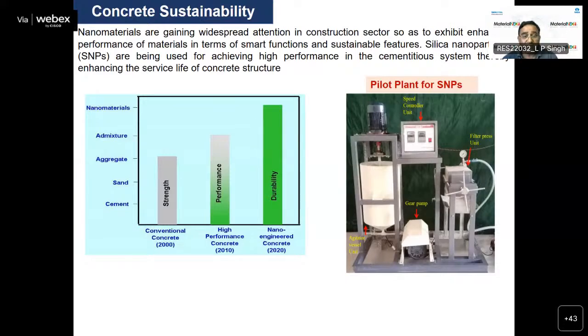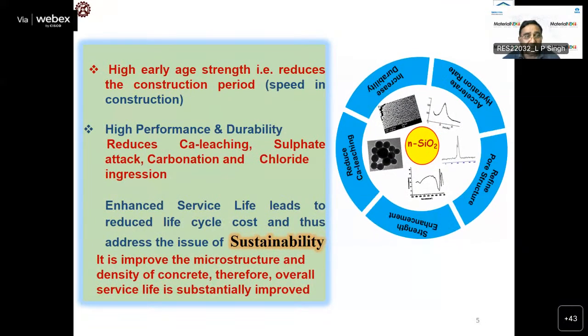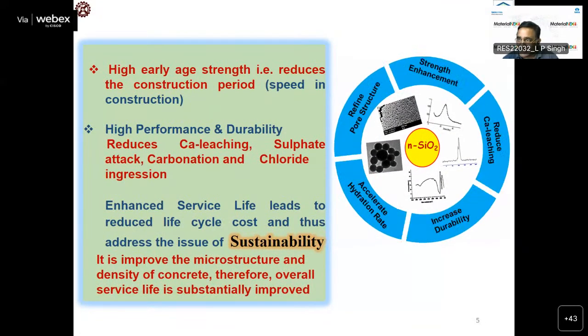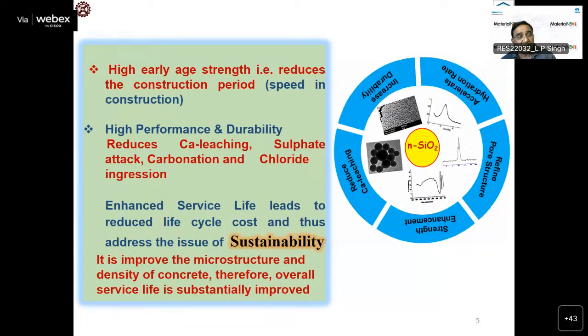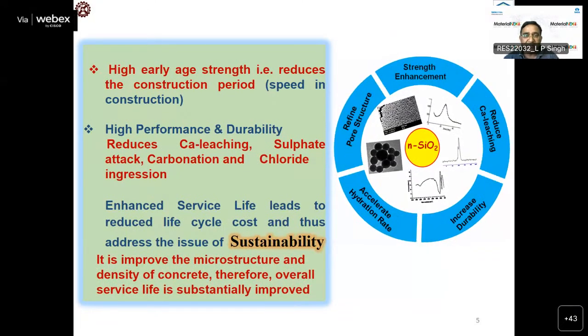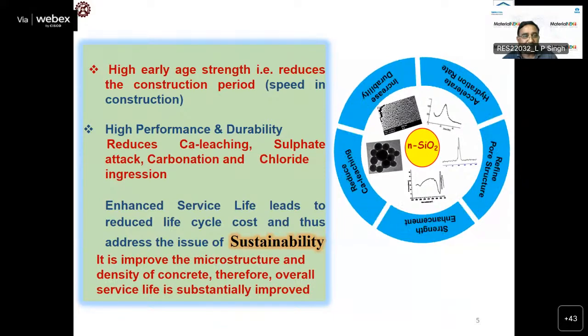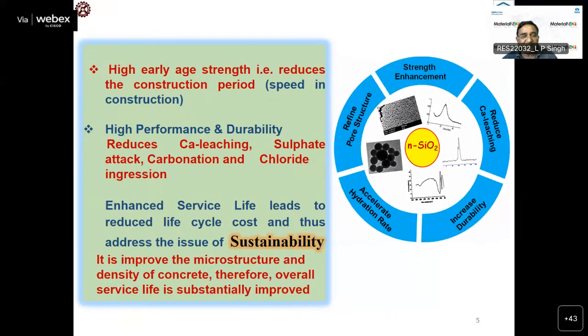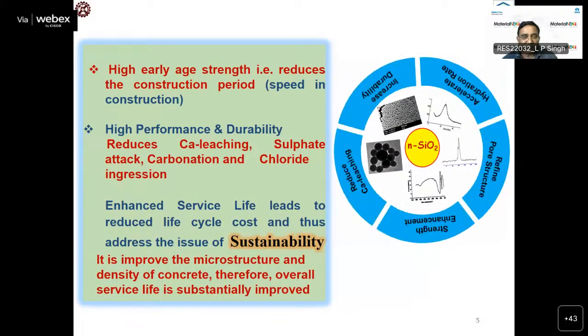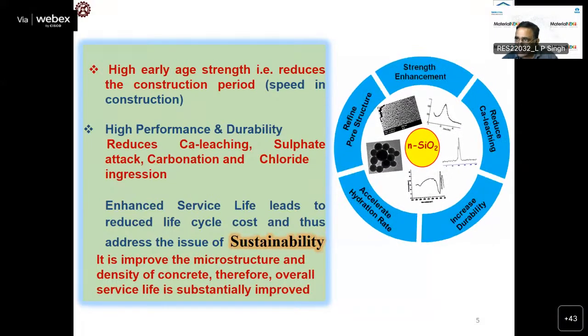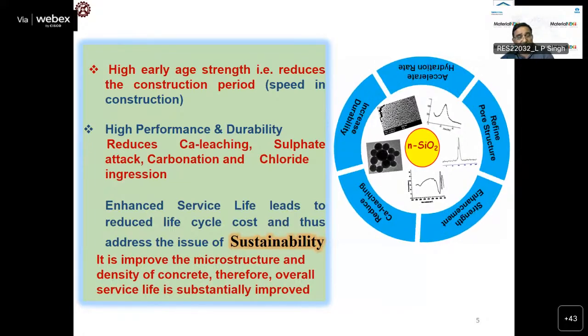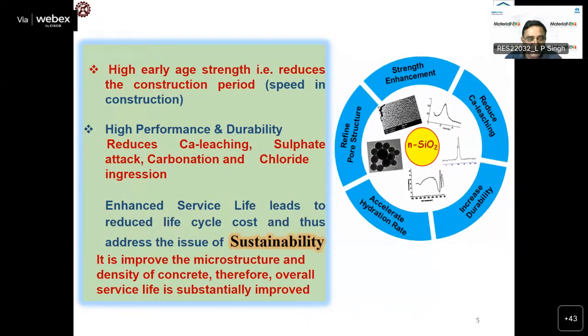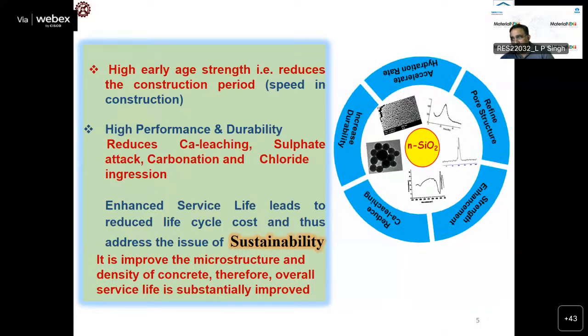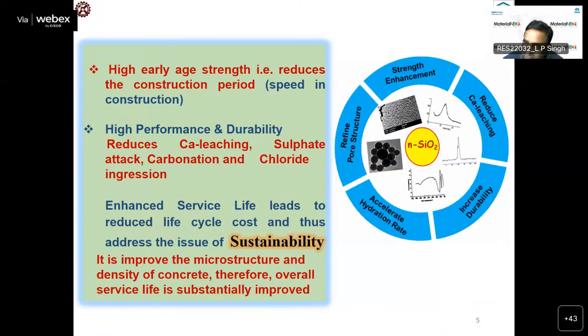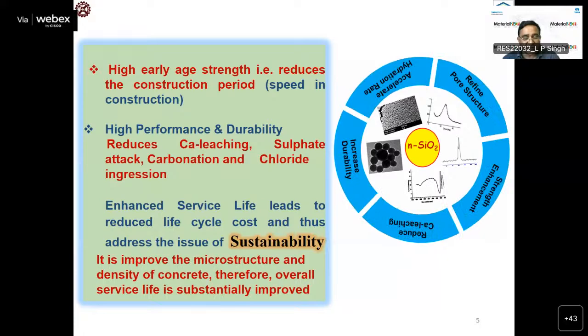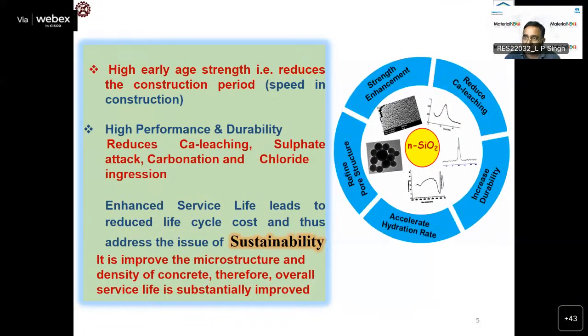This technology we have also transferred to the market, and there are three basic advantages we get when we add these nanomaterials to the concrete: high early stage strength, that means it will reduce the construction period, and higher performance and durability because it reduces calcium leaching, sulfate attack, carbonation, and chloride ingression. Therefore, we have enhanced service life that leads to reduced life cycle cost, and thus the real challenge with concrete that we call concrete sustainability can be addressed by the use of nanotechnology.